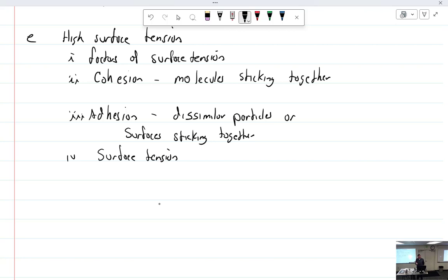When you deal with surface tension, there's this weird phenomenon whereby if we have a tank of liquid penetrant, and we drop a part in the liquid penetrant and leave it in, it affects the surface tension. You have less surface tension while it's in the tank. So the fluid, even though it's under pressure, has less of a tendency to seep into the cracks. When you pull the part out of the tank and lay it down, and the liquid now covers it but it's not immersed, the surface tension increases, which tends to make that fluid flow into the crack at a much higher rate.